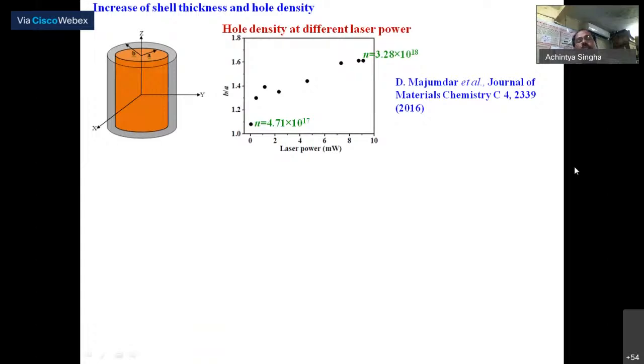Yeah, from analysis we can get the peak position. We can get the charge concentration within the nanowire by increasing the laser power.